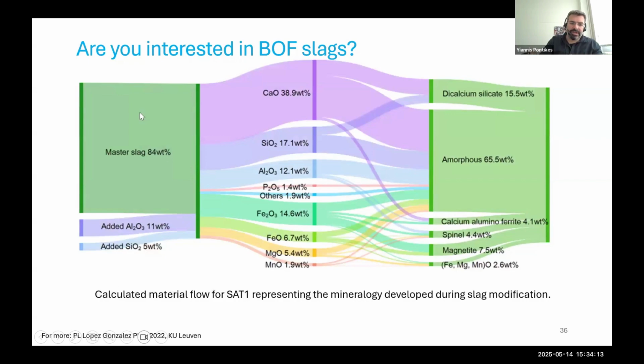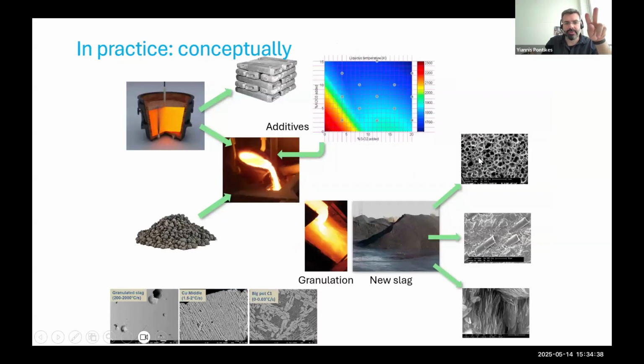And if you want again to visualize in a Sankey diagram, 84% was the master slag, addition of alumina 11 and silica 5, and you have now this final chemistry. Interestingly, because you have higher calcia here compared to the blast furnace, you also have calcium silicate, which is a classical phase in cement, and high amorphous content. And this is behaving quite nicely, as you've seen before, both from an alkali activation perspective and a blended cement perspective.